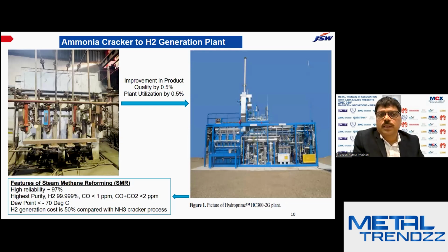Conventionally, hydrogen was generated through ammonia crackers using raw ammonia, which is very toxic in nature. So the idea was to generate hydrogen through either gray hydrogen, blue hydrogen, or green hydrogen. These are three different processes. We have started with gray hydrogen. Gray hydrogen is nothing but generation of hydrogen using natural gas. Here the purity is better than the conventional hydrogen generation method, and the cost is also 50% compared to the ammonia cracking process.